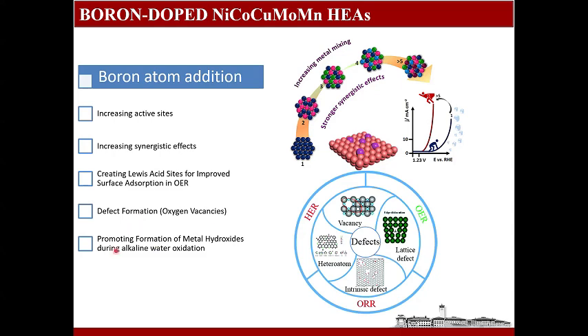And it might promote the formation of the metal hydroxides during alkaline water oxidation. So the introduction of these defects might increase the number of vacancies, and then it might increase the lattice defects, and then they might result in the improvement of the electrocatalytic activity together with the synergistic effect.